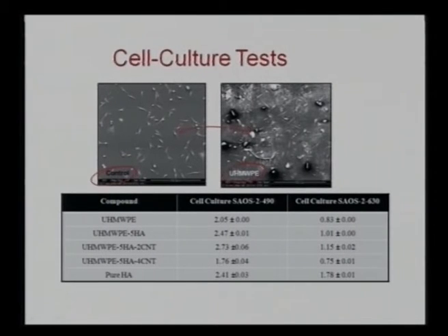In this case, we have utilized the SAOS-2 cell line, which is a human osteosarcoma cell line, at a wavelength of 490 nanometer and at 630 nanometer. And we can see, quantification-wise, that we are seeing approximately similar cytocompatibility. The overall count of the cells, through a particular quantification technique using a UV spectrophotometer, we can see that the particular counts are approximately similar. They are not deteriorating to a stronger extent.